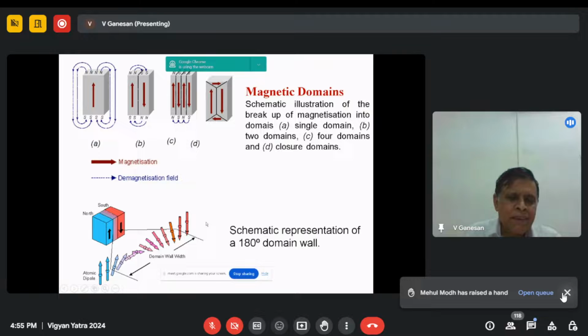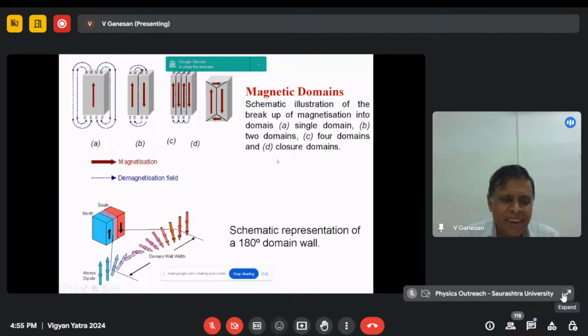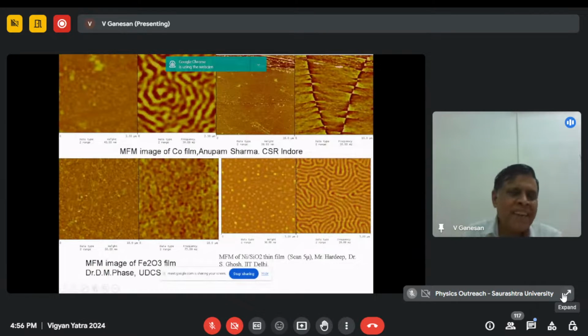So from an up domain to a down domain, it will not happen at the next atom, assuming atomic dipoles are there. It will not happen if you suddenly want to flip; you need a large energy. It flips over a period of lattice parameters, so it can be 10 atoms, it can be 20 atoms. Typically it is about 100 atoms. Therefore, the Kittel wall, where the magnetization goes from up to down, is at least 50 to 100 nanometers. And this gives you a very beautiful concept. As long as you are in an up domain, no change. As long as in a down domain, no change. The moment you cross from one domain to another, a huge magnetic contrast is available for your force, and that force is measured. I'm giving you an example.